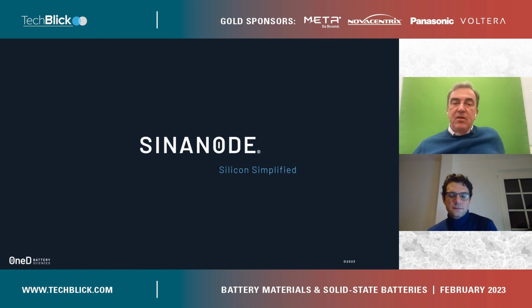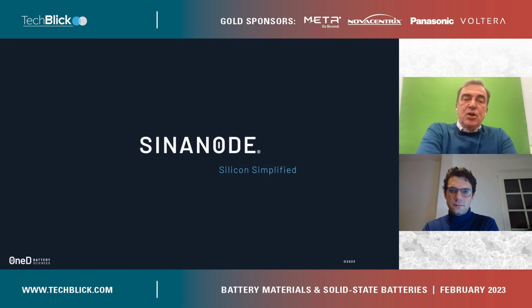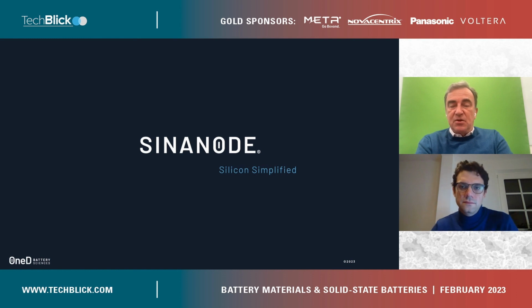Yeah, so today for our customers, we cycle those EV cells to about 1,000 cycles at half a C or 1C rates and achieve between 70 and 80% capacity retention, depending on the amount of silicon. I think that this new version, where we have added the special surface treatment, has had a dramatic effect on the capacity retention. We present those data to customers under NDAs because it's brand new data, and it invariably leads to a lot of questions about the effect of this special coating. We filed a patent application, but it's not yet published, so we have to be careful.